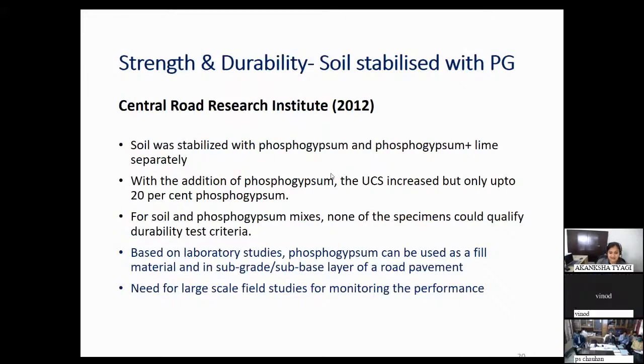However, in the later slides, you will get to know why the UCS decreases. In some of the reports you will see that you add some admixture, the strength increases and then that decreases. So basically, it has to do with the reactions taking place within the soil admixture mixtures. For the soil and the phosphogypsum mixes, none of the specimens in this particular study qualified the durability test criteria. So I would say that this also depends on the type of the soil, as we saw in the earlier slide, which type of soil you are using, and whether you are using only phosphogypsum alone, or you are going to use lime or other types of admixture.